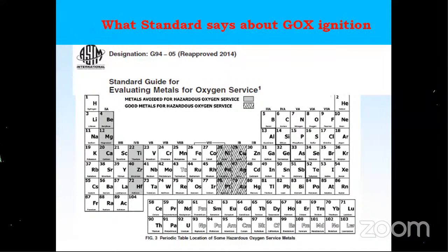Till today, only the SpaceX and Blue Origin teams, that is Jeff Bezos's Blue Origin team, are working on this material, and they have almost frozen the composition. I don't have any idea what the composition is, but I know this much, it's a nickel-based alloy. They have developed an alloy which can resist ignition in oxygen at temperatures as high as about 800 degrees centigrade. This is needed for what we call the oxidizer-rich preburner, oxidizer-rich staged combustion, that means oxygen-rich staged combustion. Only the Russians have mastered it. Their engine called RD-170 uses hot oxygen.